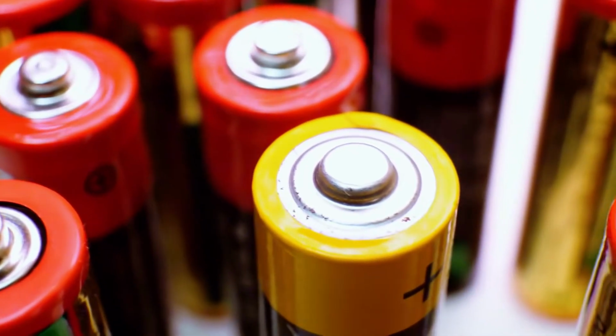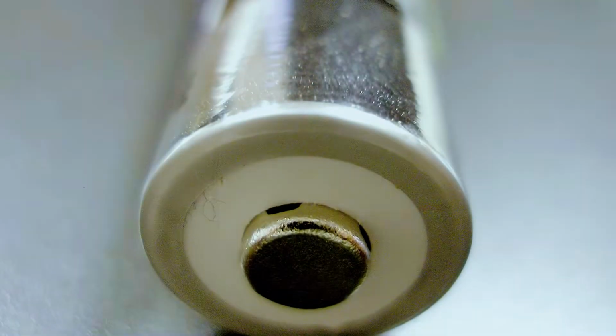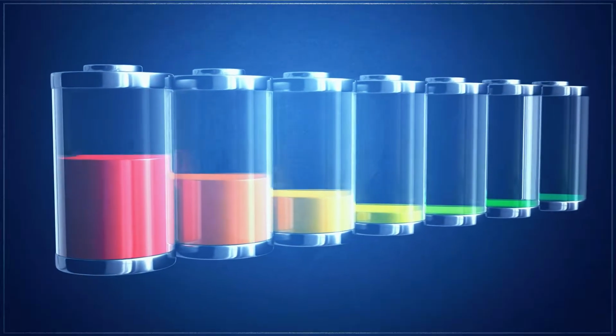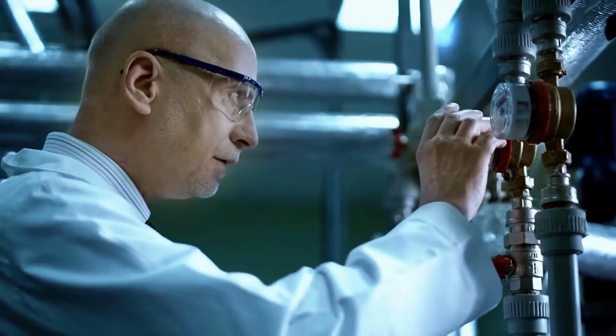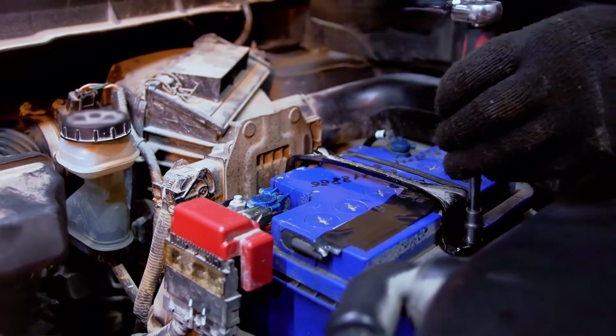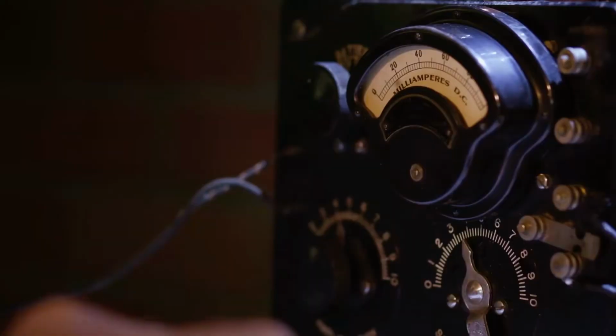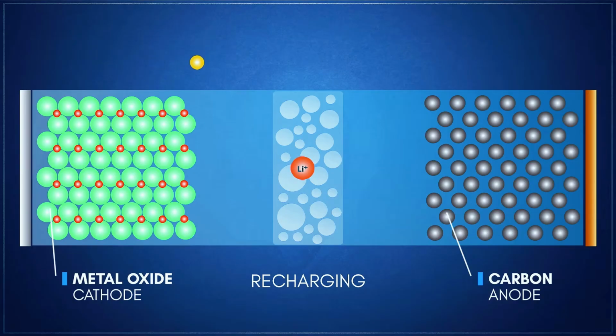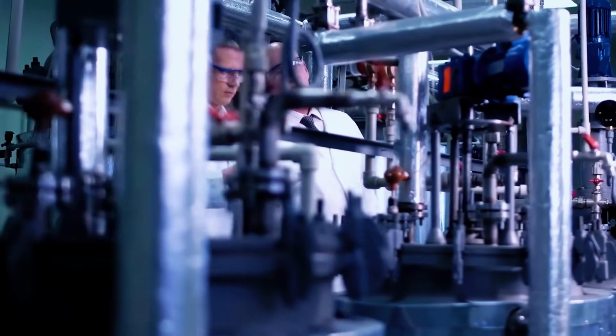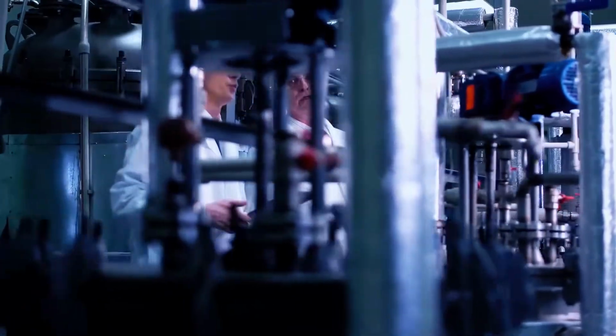The next meaningful leap came in the 1990s with nickel-metal hydride, NiMH. Toyota built the original Prius around it. Lighter than lead-acid, more energy dense, more reliable. It worked well enough to launch the hybrid era. But NiMH had hard limits: energy density too low, self-discharge too high, and temperature sensitivity that made it unsuitable for a true long-range electric vehicle.